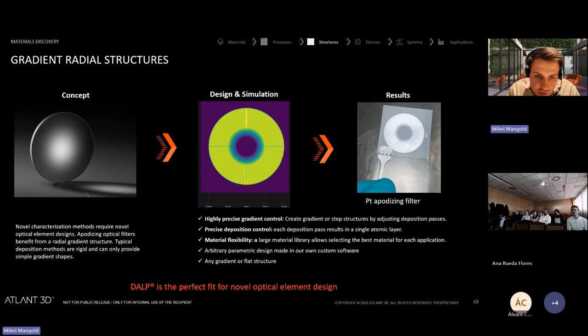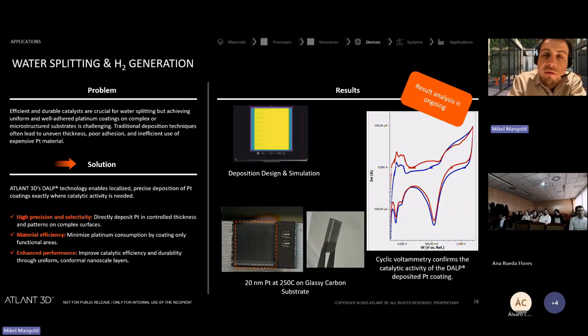And then I want to show another one, which is the hydrogen catalytic behavior. We have now 4 or 5 projects on that. You know that obviously many want to have hydrogen in the future, but it's still very expensive to produce hydrogen from water. So there is a lot of research to be made to find a way to reduce the cost of the water splitting experiment. That's why we're working on it. We use platinum, and you see that she coated 20 nanometer of platinum, and then she demonstrated that we were able to split water into hydrogen by using less catalytic material, which is one of the cost drivers, and rare minerals that you don't want to use too much because we don't have enough.